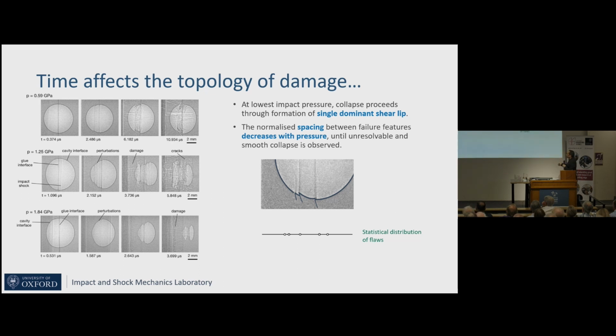And we can use a theory of statistical distribution of flaws. We can say in any solid, on any surface, there's going to be a variation in the position of those atoms. There might actually be a macroscopic defect, in fact. But we can have a statistical distribution of flaws. And if they all grow at a different rate, because we're talking about dynamics, the presence of a flaw is to relax the material around it. And so as that flaw grows, you can see a shadow that's growing out, and it's extinguishing these other failure embryos. And those embryos are no longer allowed to grow. And so the final number of fissures that we get, or failure features that we see, is directly a response of the distribution of source sizes. In other words, what is going to fail first, and how hard you hit it, and where the energy is going.